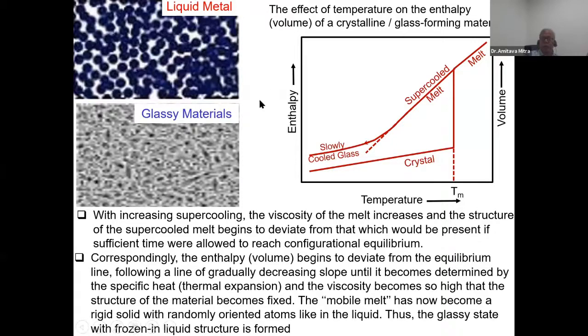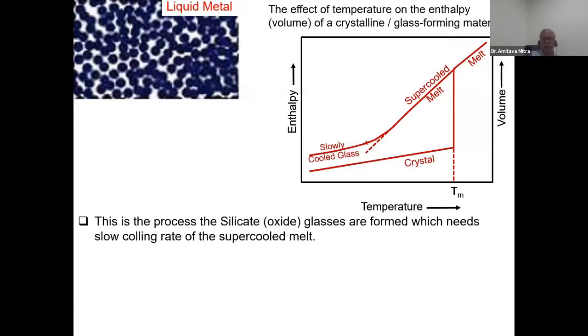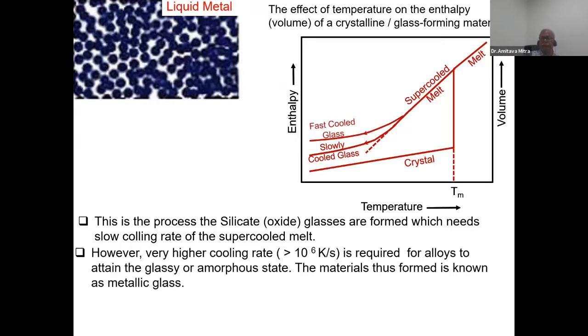This is called the frozen-in liquid structure. This is very common for silicate glasses, which form and need slow cooling of the melt. But if, in certain alloys, we cool very rapidly, this is fast cooling, compared to the slowly cooled case used for silicate glasses.